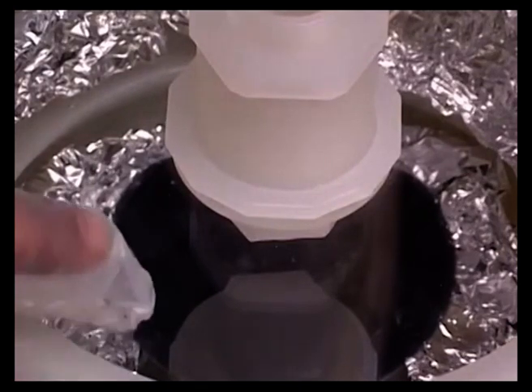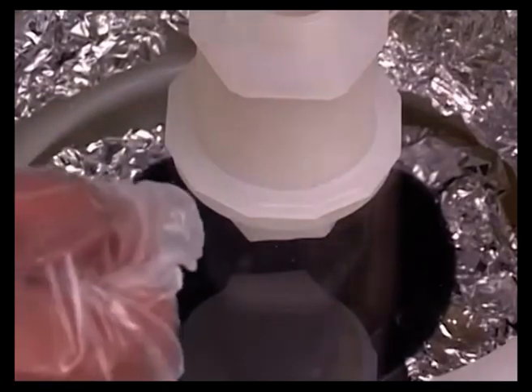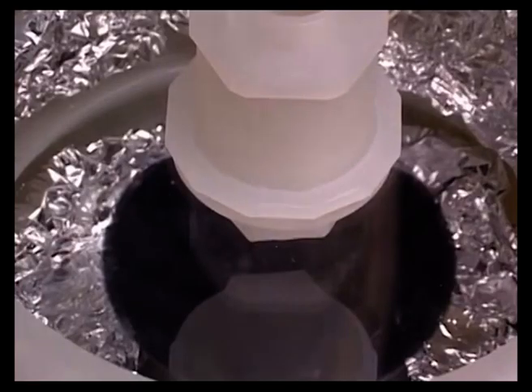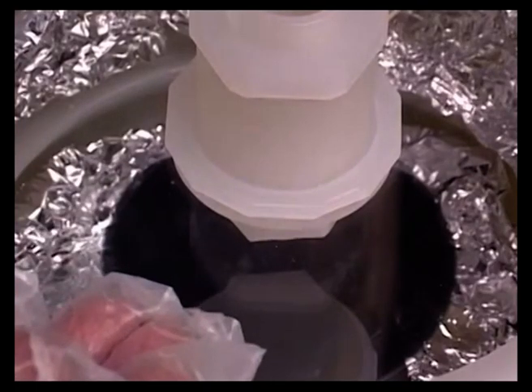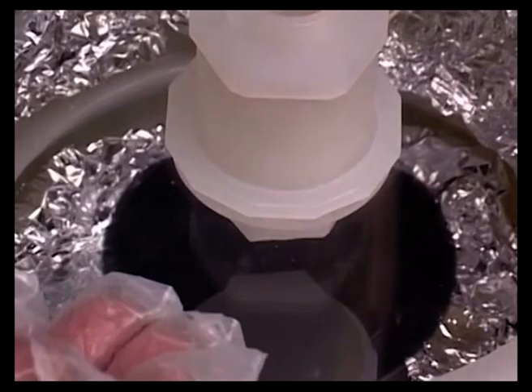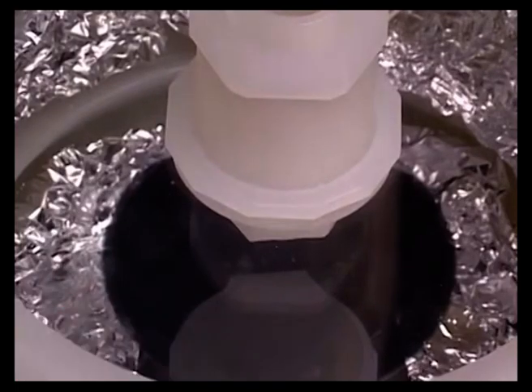So I am going to now spin coat the photoresist on top of this wafer by pouring the resist and then executing the RPM cycle. And the moment the resist is spin coated, we also need to take this for the two step heating process, which I am going to describe in a little bit.